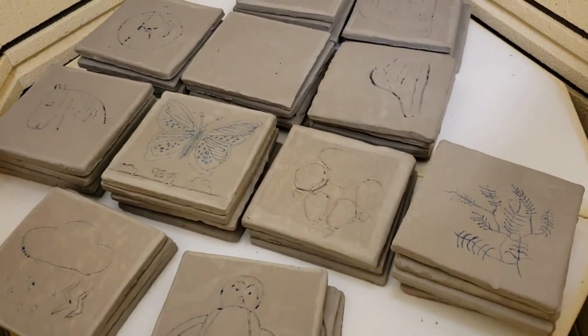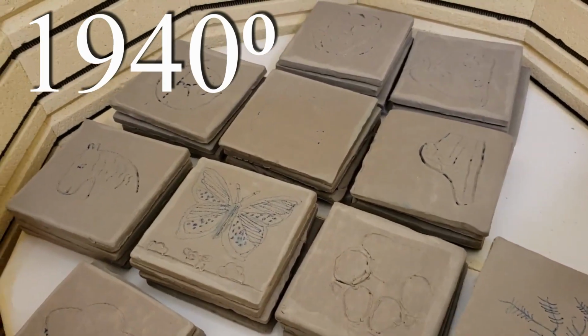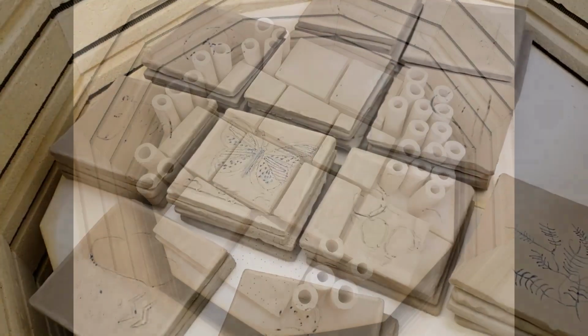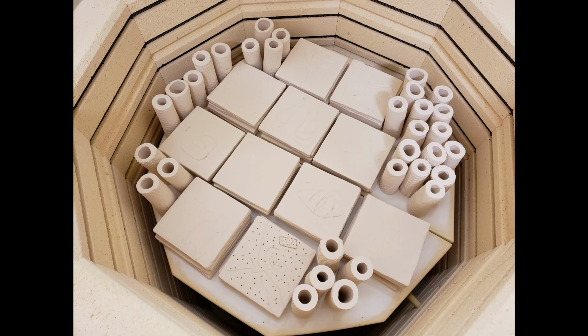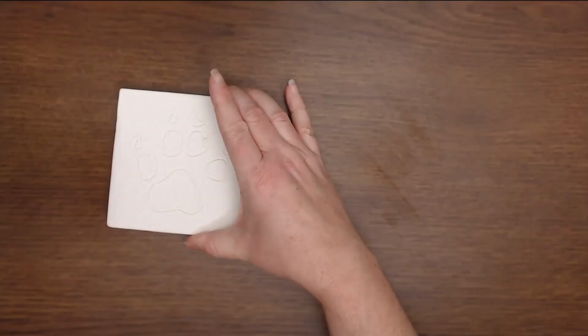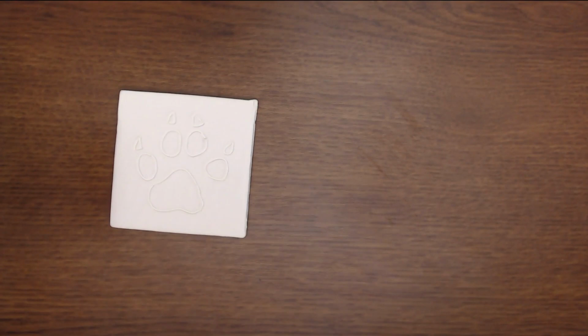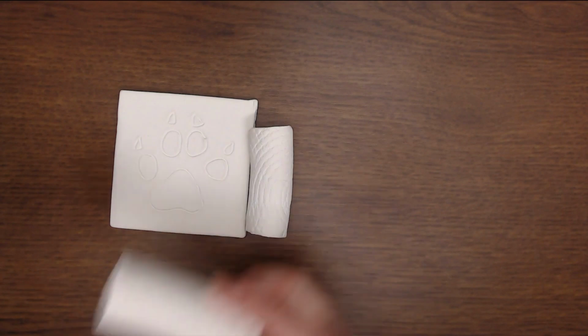During the bisque firing, the temperature raises to 1940 degrees Fahrenheit. During this, the clay turns a white color and takes over 24 hours to fire and cool before the pieces can be removed. This temperature is much hotter than your oven at home, which probably only goes up to about 500 degrees.